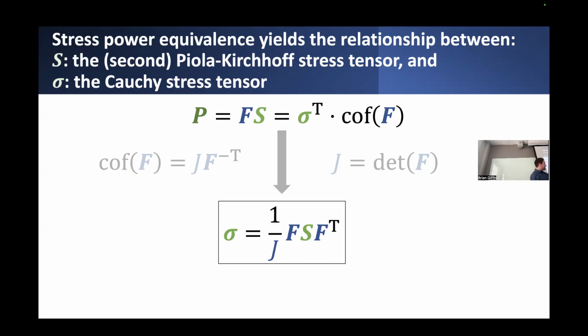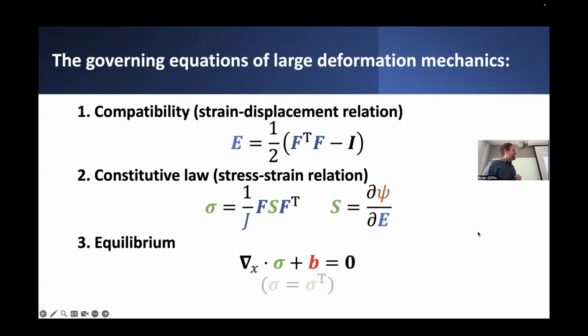What's interesting about this expression is, certainly we know that the Cauchy stress has to be symmetric. That was a requirement in order for moment equilibrium to be satisfied. It turns out that the second Piola-Kirchhoff stress is also symmetric. You can see that just by virtue of how this relationship unfolds. If we're left and right multiplying by the same tensor, F and F transpose, then the resulting matrix gives us back a symmetric tensor. So both of those measures of stress are symmetric, which is kind of nice. It's convenient. But at the end of the day, that finally comes together.